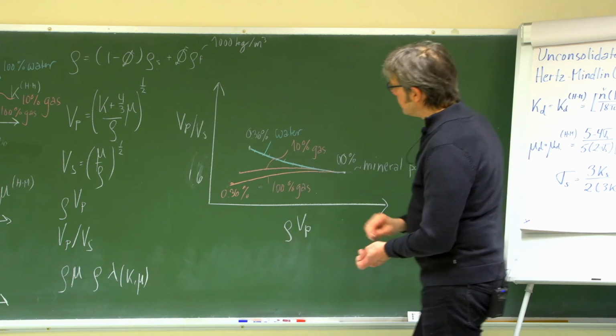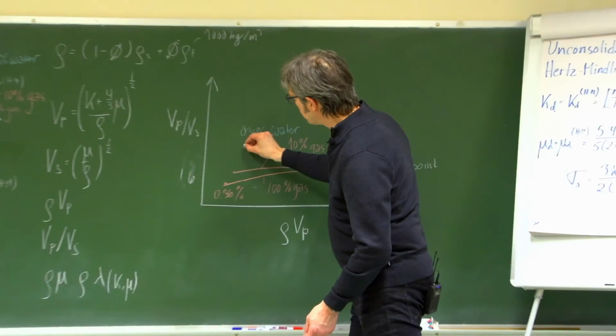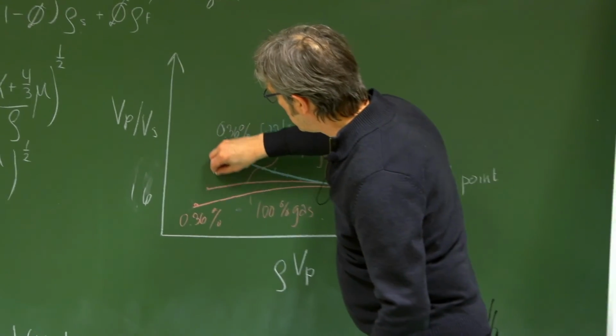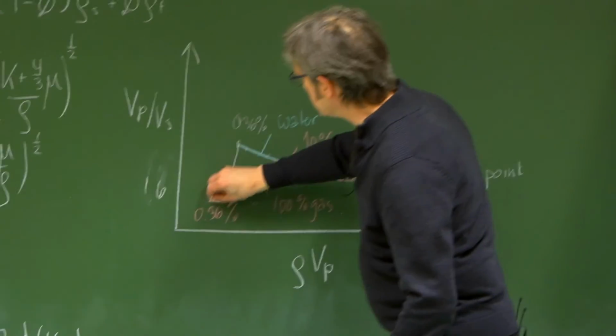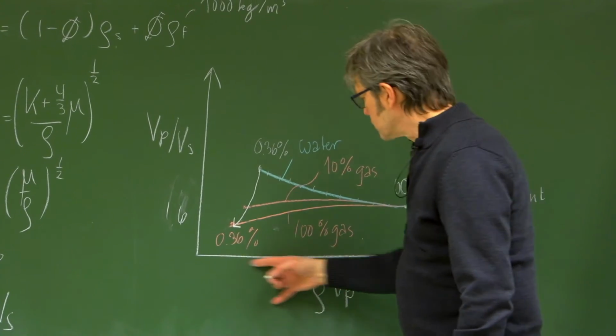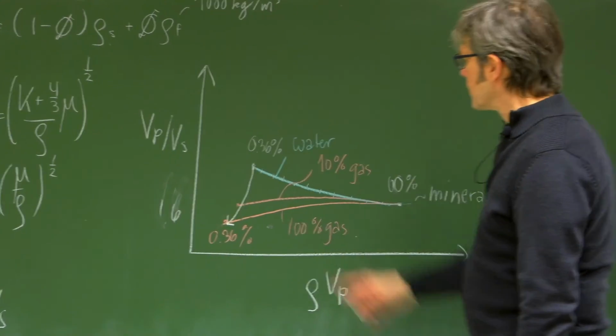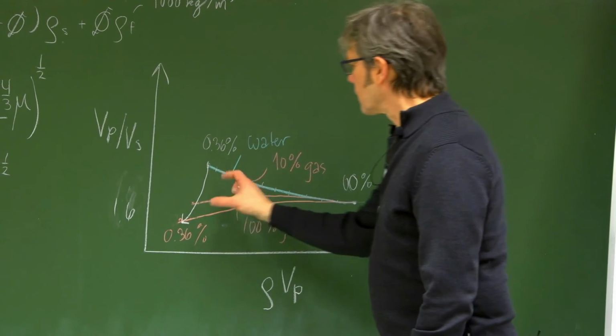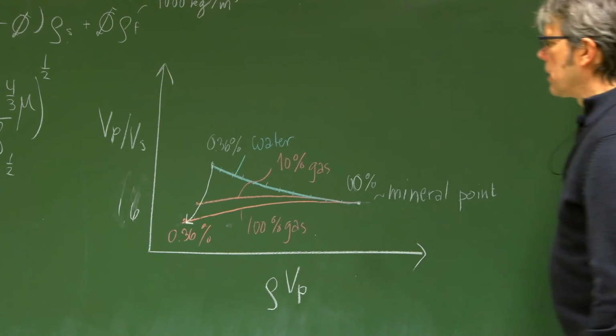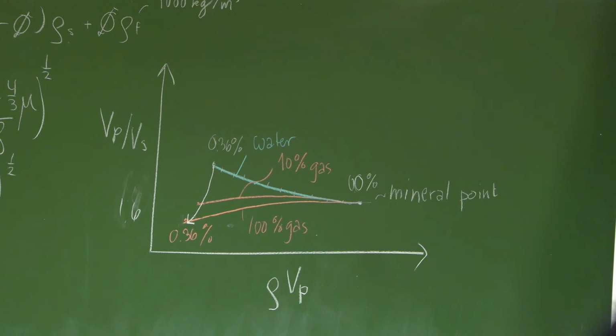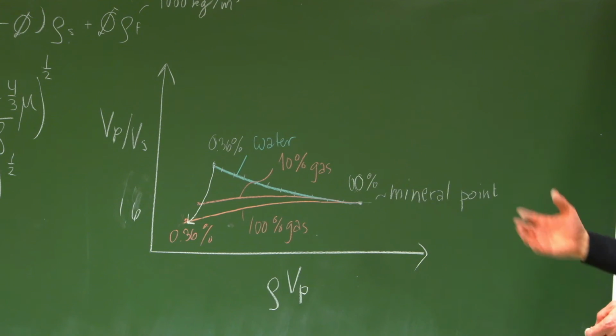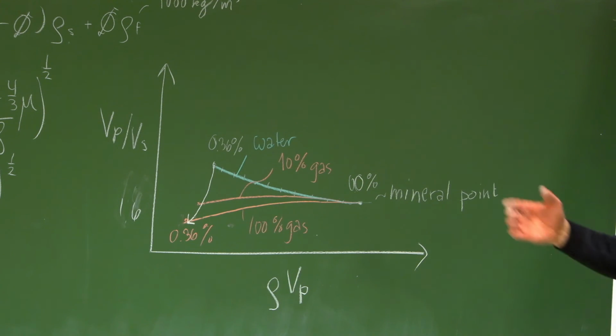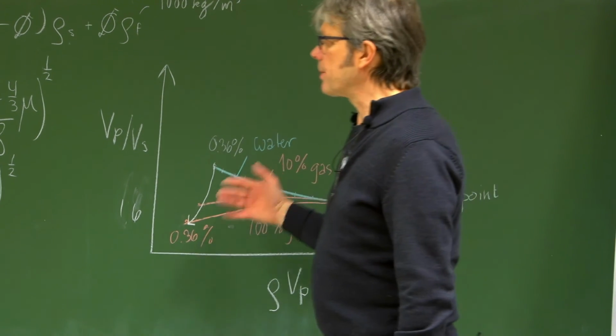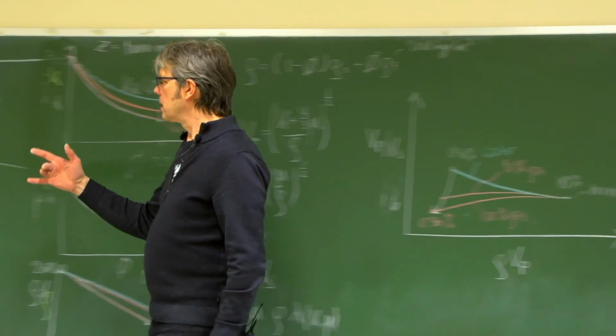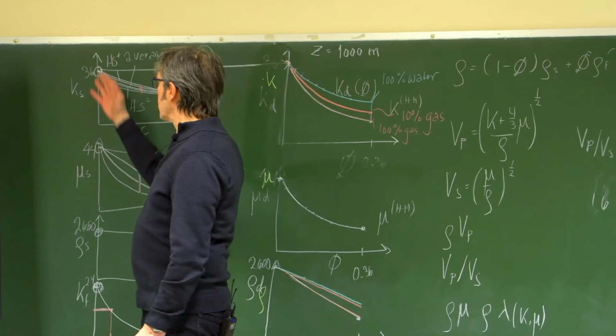So we see that the fluid effect here for the same porosity is quite dramatic when it comes to the VP/VS. It's lowering the acoustic impedance, but it gives a larger effect on the VP/VS. Okay, so this is the template in case I use a clean sand.